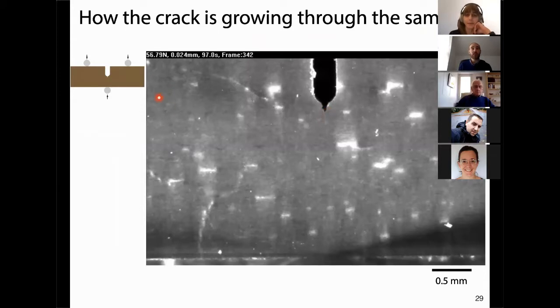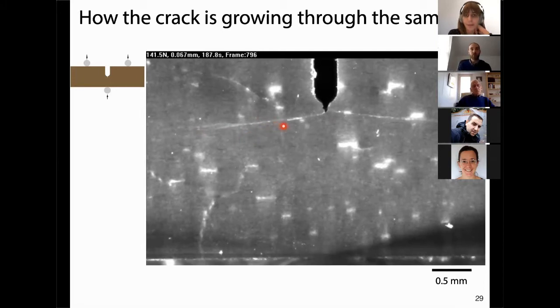So this is a sample that's been tested in bending, and we really try to open this crack. What you can see here is that the crack starts here and actually gets highly deflected by the microstructure, and it grows in a very stable way. And we get to the second branch here that grows almost at the same pace. So you get some branching, you get a lot of different mechanical toughening mechanisms.